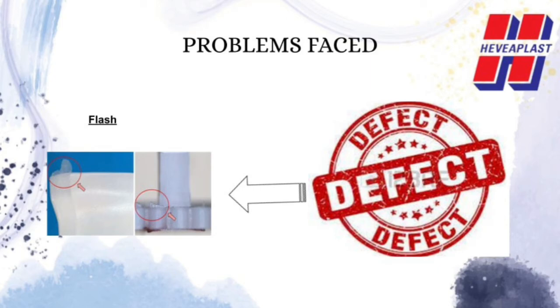Typical routes for escape are through the parting line or ejector pin location. This extrusion cools and remains attached to the finished product. Flash can occur when the mold is not clamped together with enough force, which allows the plastic to seep through. The use of molds that have exceeded their lifespan will be worn out and contribute to the possibility of flash. Additionally, excessive injection pressure may force the plastic out through the route of less resistance.